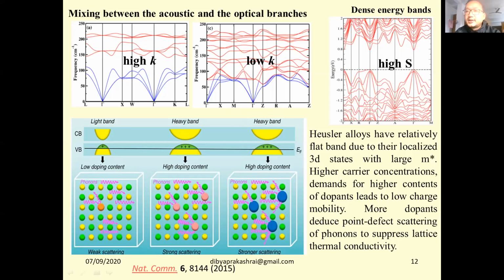So light band materials are not good thermoelectric materials, because the density of states is not that dense near the Fermi level. Another thing is that the light band will have a lower effective mass. If the effective mass is low, then the motion of the charge will be high, or you can say the charge mobility will be high.